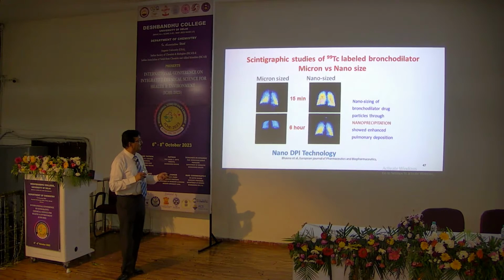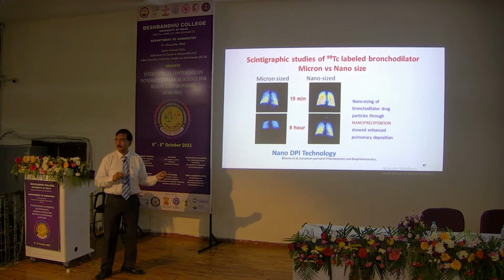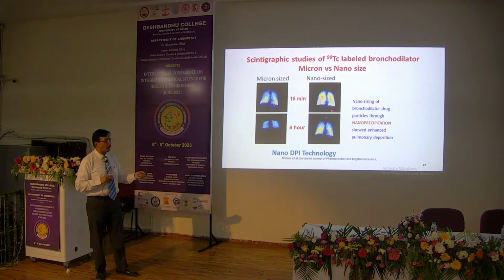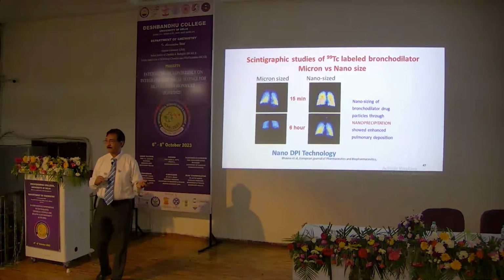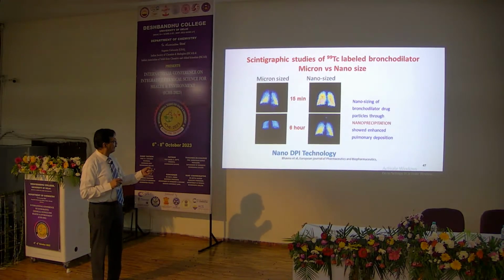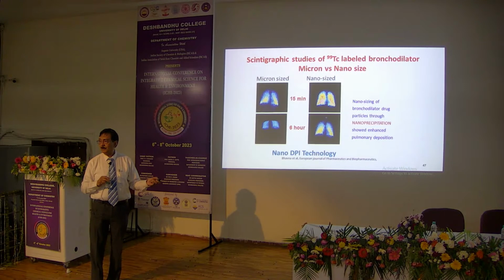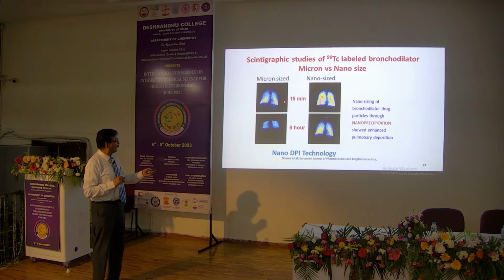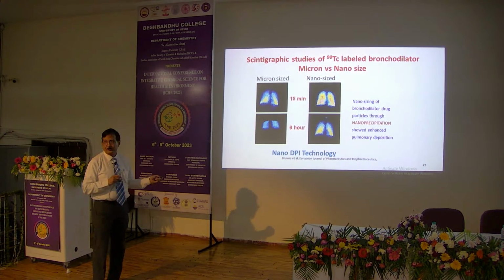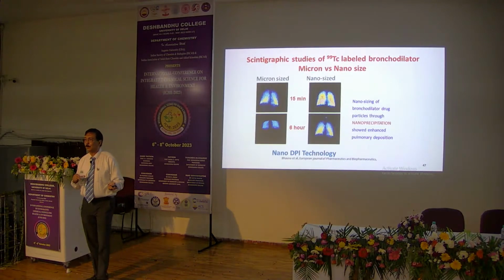Then we tried to develop particles, modifying their density and particle size, and we could achieve a deposition of about 60 to 80%. You can see that when particles are tagged with technetium 99, after 15 minutes the lung fields are much brighter compared to the micron size particles. Most surprisingly, after 6 hours the drug was still there, while with micron particles there was no drug. So it was acting as a depot.